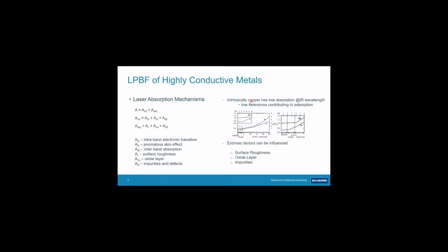So intrinsically, and this is shown here, in the infrared region, there are not a lot of electrons contributing to the absorption of laser light with an infrared laser wavelength. So both copper and silver by nature will not absorb a lot in the infrared or near infrared region. What can we modify? Of course, we can modify the surface roughness. We can introduce oxides on the outer surface of a plate, or as I will show later, on a powder bed, and all kinds of impurities, which could also be alloying elements.